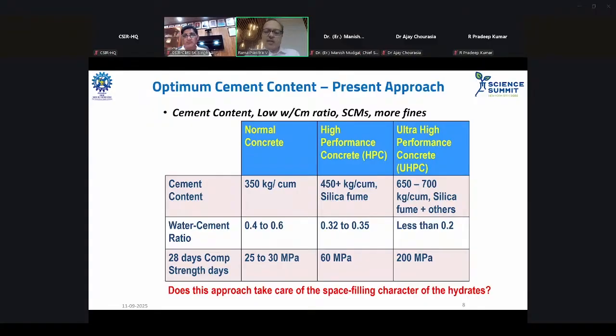If we have to get higher strength of concrete, let us say 50 to 60 MPa, all that we need to do is increase the cement content to 450 kg per cubic meter, plus use silica fume, etc. Reduce the water cement ratio, and you would get that. Further, if you go higher and higher as far as concrete strength is concerned, your cement content would go to 650 to 700 kg per meter cube, silica fume plus others would add, and the water cement ratio would be 0.2 or even less than 0.2. Therefore, we can produce even ultra high performance concrete of the order of 150 MPa to 200 MPa.